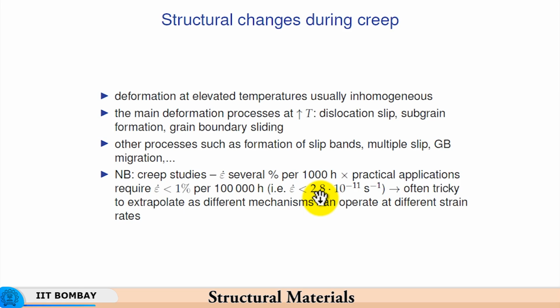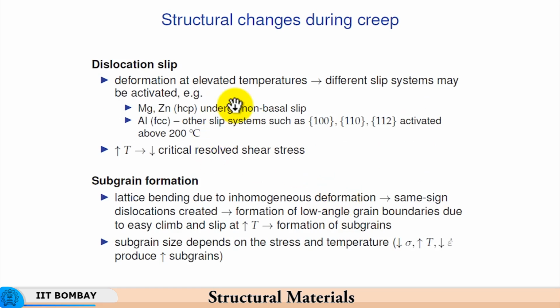Mind you, the loading is below the yield strength, the yield point of the material, and so your creep strain rate has to be maintained below a value of, let us say, 2.8 into 10 to the power minus 11 seconds inverse, right. So this is a strain rate which is a total outcome of various mechanisms operating concurrently. Now, different mechanisms and different slip systems can come into operation, or get activated, at high temperatures. So that is how the structural changes take place during creep.